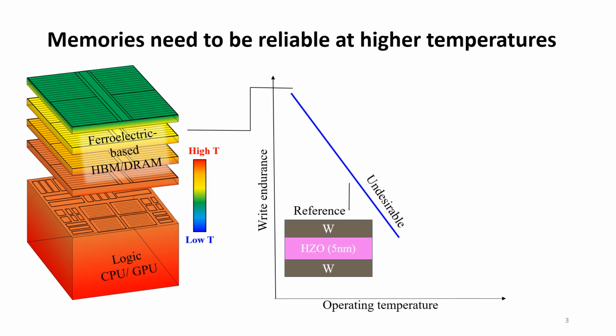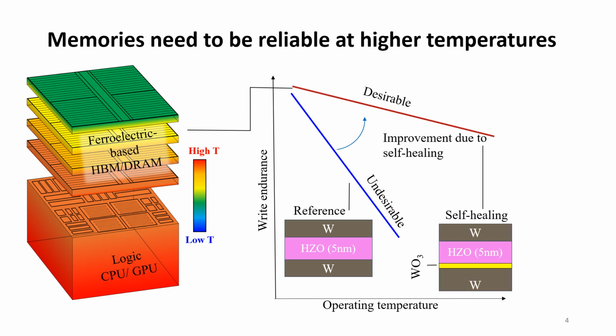However, we know that ferroelectric memories suffer from reliability issues and it gets even worse at higher temperatures. So ferroelectric memories fail very quickly when we go to higher operating temperatures as shown by the blue curve here. But this is not something desirable for memory and logic applications. For memory and logic applications, we want memories to be reliable for a wide range of temperature, from room to the elevated levels, as you can see here in the red curve. So in this work, we will be presenting a temperature activated self-healing process by inserting an oxygen reservoir layer to improve the endurance of ferroelectric capacitors at higher temperatures.